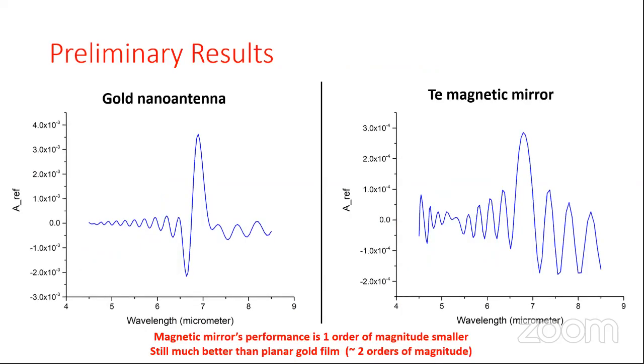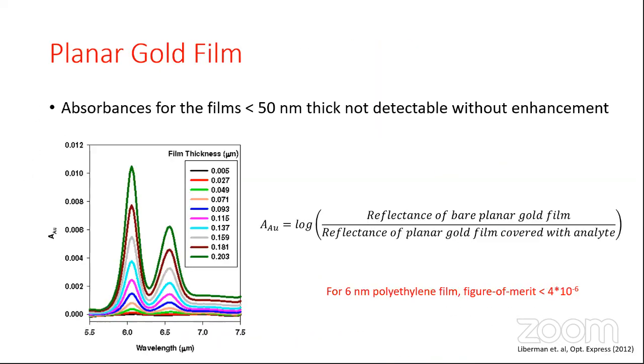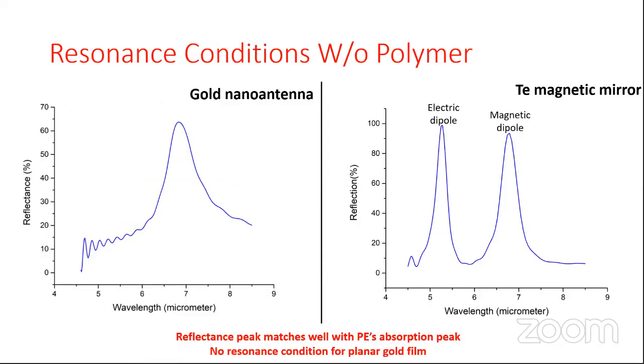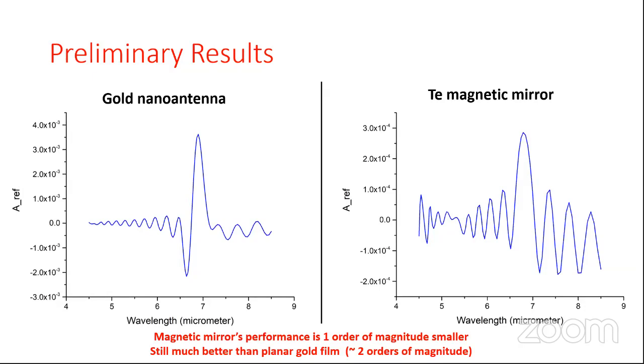And here, this is the crux of the study, the preliminary results of the figure of merit, the enhancement numbers. On the left, you could see the gold nano antenna. The figure of merit is roughly 4 times 10 to the minus 3. And for the telluride magnetic mirror, the peak is around 3 times 10 to the minus 4. The wavelength at which the peak is shown corresponds to 6.8 micrometer, more or less, which is expected. But as you could see, the magnetic mirror's performance is 1 order of magnitude smaller. And as I showed before, for standard unpatterned planar gold film, the figure of merit is around 10 to the minus 6. So although the magnetic mirror's performance is 2 orders of magnitude higher than that, it's still an order of magnitude smaller compared to the gold nano antenna array.